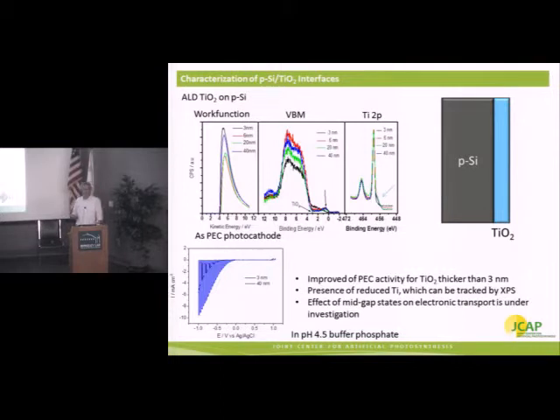In any case, what we find is that application of a thin TiO2 layer does stabilize the photoelectrode, but the thicker you get with the TiO2, actually the better the performance gets. So here, you can barely see it, but the black curve behind this blue curve is for a 3 nanometer thick TiO2 layer. The blue curve is for a 40 nanometer thick TiO2 layer. This means right off the bat that we're not dealing with a tunneling process. So charge is transported through a 40 nanometer thick layer of TiO2 on the surface.